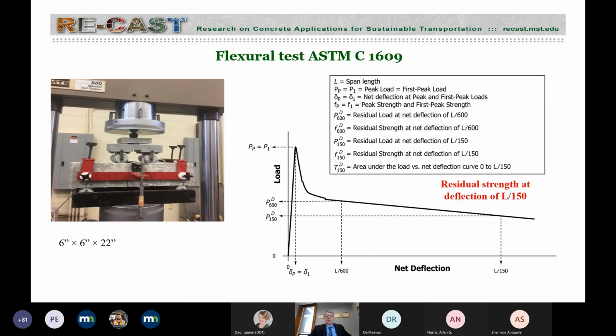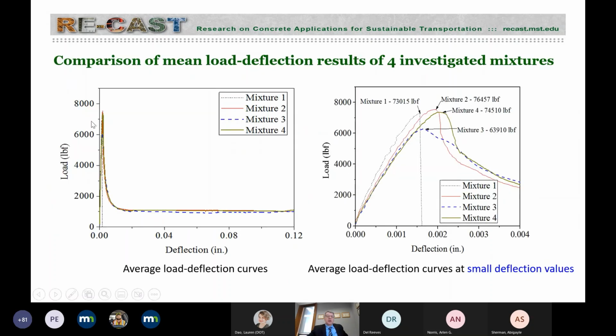We did also the flexural strengths. We're interested in the residual strengths at the deformation of length of the sample between the 2 supports over 150. Experience from previous testing told us that we need to get at least 20%. So you could see the load deflection. This is typical of synthetic fibers. Once you reach the peak load, you have a very fast and sudden reduction of load carrying capacity, but the fibers are still sustaining some load, and so you still have a lot of deformation and bridging the cracks.